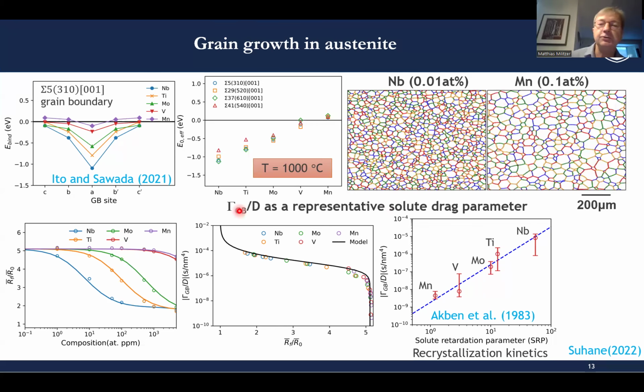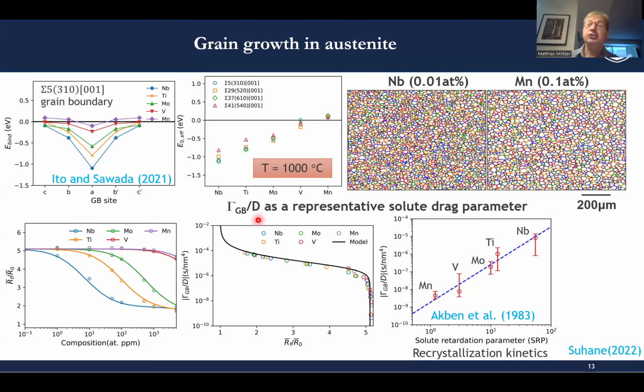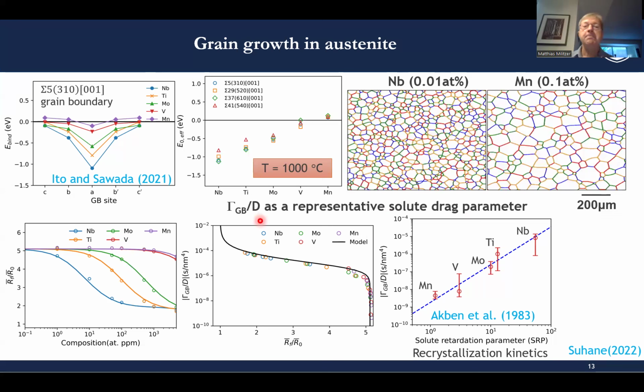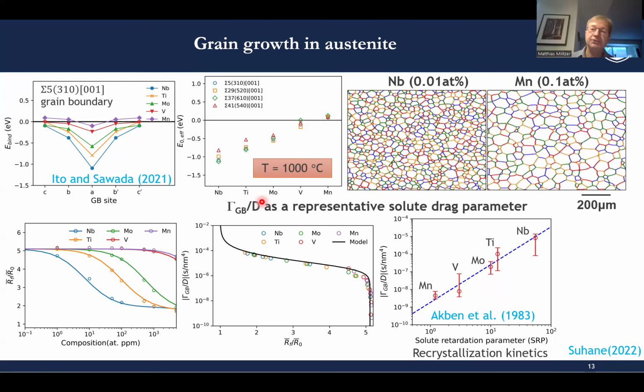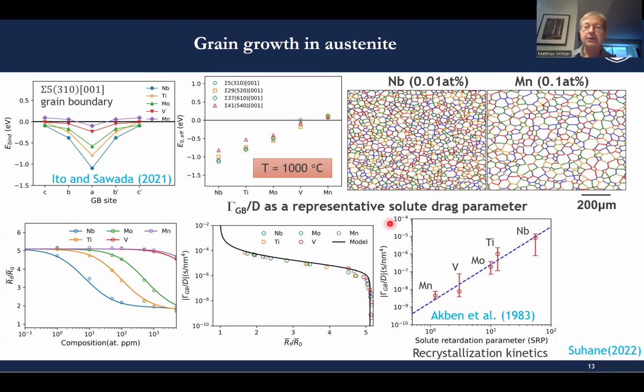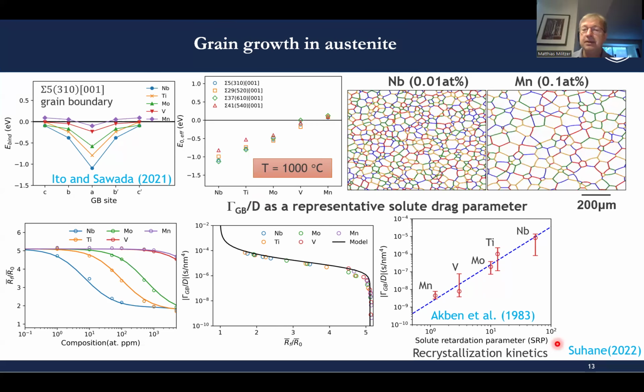And what we found is we can introduce a representative solute drag parameter, that's the enrichment divided by diffusivity, to describe the reduction or the change in grain size evolution with respect to a benchmark where there is no solute in the simulation domain, so pure iron. And in this solute drag parameter, the diffusivity, we can actually approximate with bulk diffusivity. They are relatively well known for iron because the diffusivity across the grain boundary area, which is relevant, typically scales with the bulk diffusivity. So we can compare now this solute drag parameter with a solute retardation parameter that was concluded from very careful studies in recrystallization kinetics also some 40 years ago by Akben and co-workers. And we see that the ranking is consistent with these experimental data: niobium, strongest solute drag element, followed by titanium, molybdenum, vanadium, and manganese.